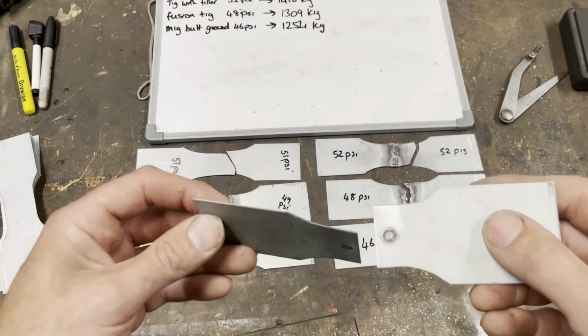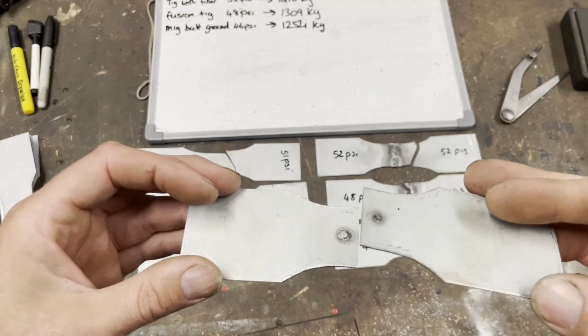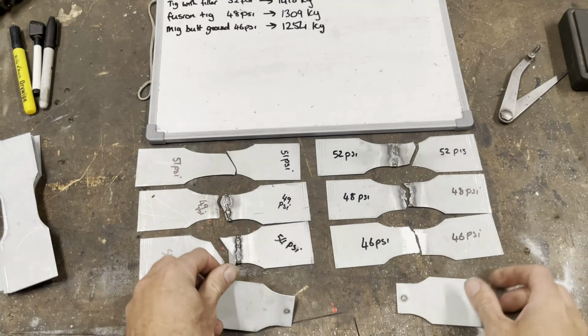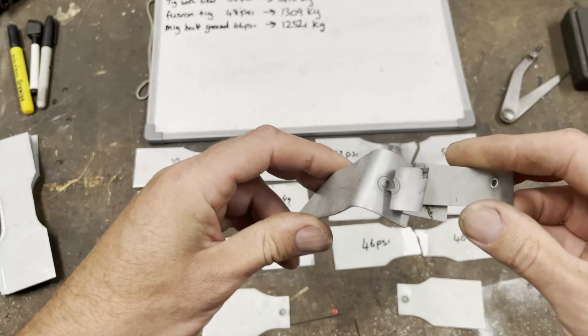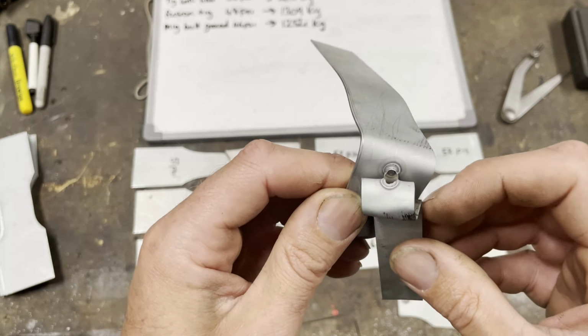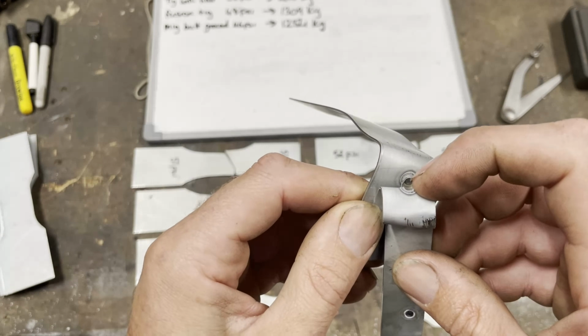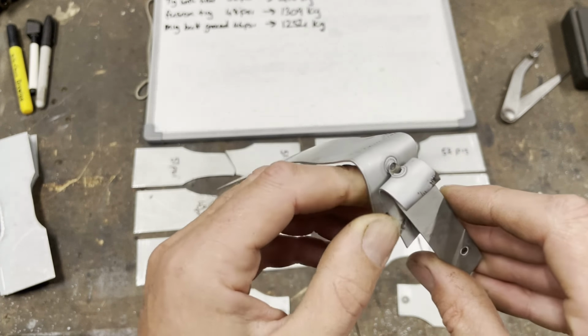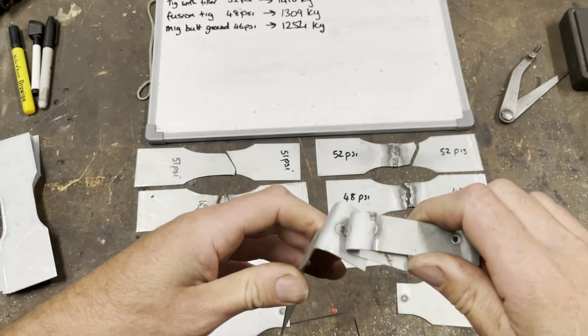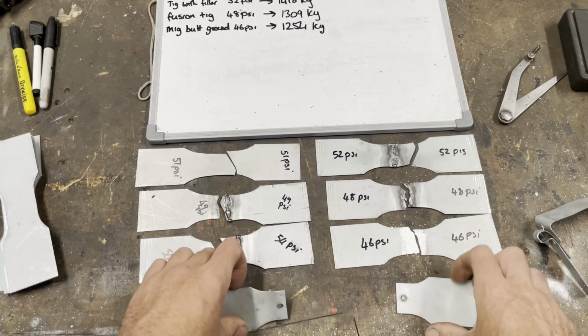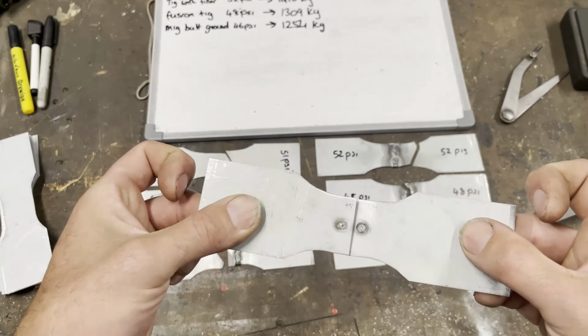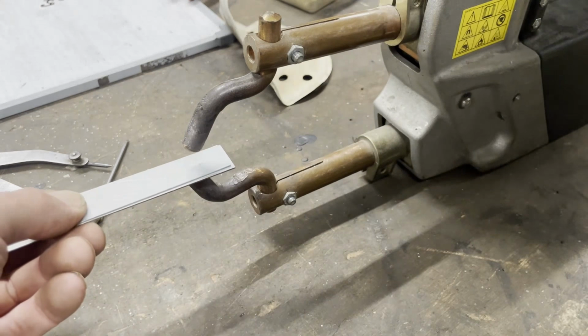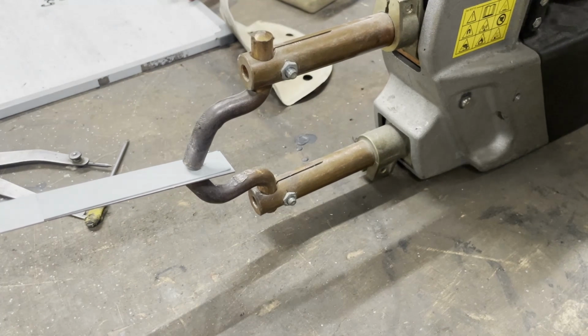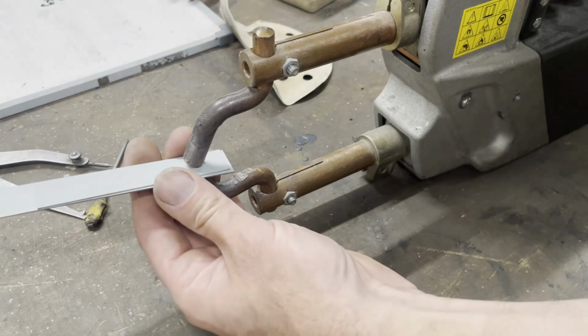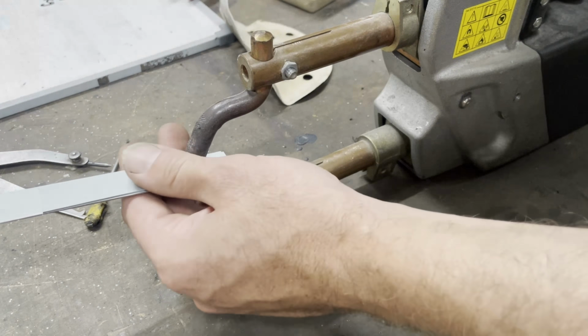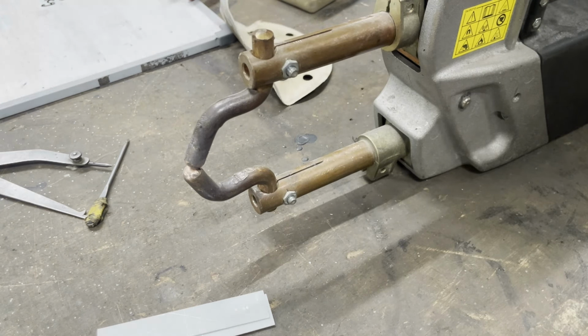That spot weld test was a complete fail. I don't know why, it's a bit concerning. I did a test before I did that, and this is how it's supposed to come apart. You're supposed to see a slug on one side and a hole in the other. And I always do this when I'm using the spot welder, but for some reason this didn't weld. I've had it before where the pressure between the two electrodes isn't enough, and that will cause a failure, but I'm thinking the pressure isn't that bad.